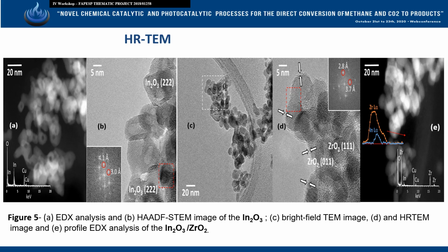For the sample indium oxide on zirconium oxide, it is interesting to note that all the particles are covered by a thin layer. Interestingly, the indium signal is located at the edge of the zirconium oxide particles, supporting the idea that the amorphous shell corresponds to indium oxide.